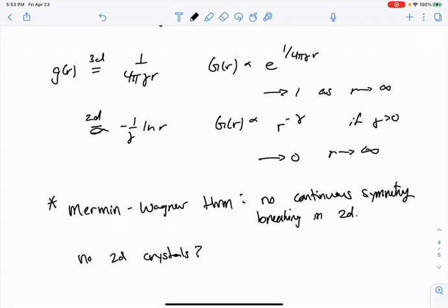So this algebraic decay is really, really slow. It's in fact so slow that one can keep long-range order over really large length scales. So there's a practical point, which is that continuous symmetry breaking can sure look like it exists in 2 dimensions, even though formally it cannot.